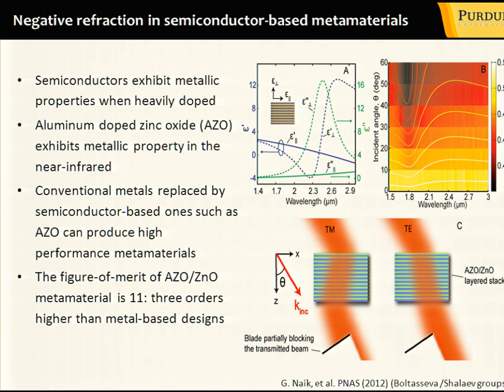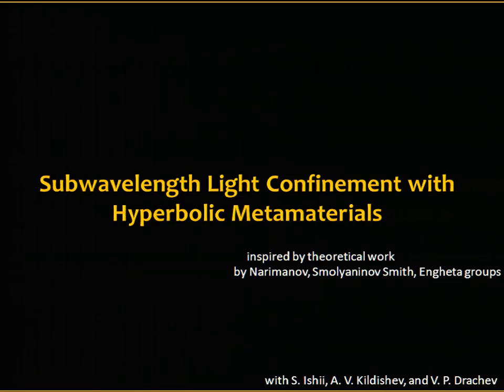Specifically, we use a stack of these plasmonic materials based on aluminum-doped zinc oxide, with zinc oxide in between, and we showed that indeed there is negative refraction in this case, with quite a decent figure of merit of 11. And by the way, if the same structure were made with silver or gold, the figure of merit would be 2 to 3 orders of magnitude less.